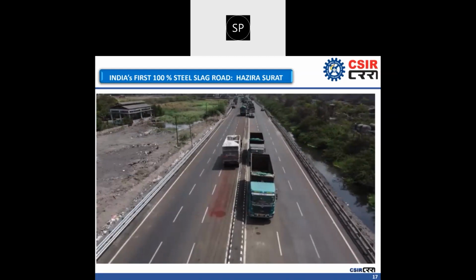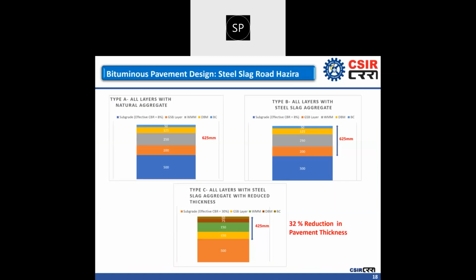We carried out the axle load survey on top of it, and we found that the axle load on this particular road is between 26 to 32 ton, which is quite the heaviest traffic we have witnessed in any section. Despite that, this road so far has not developed any sort of pothole. There is no sign of distress in it, and it is perfectly intact. In terms of the composition, we carried out a parametric study on this particular section.